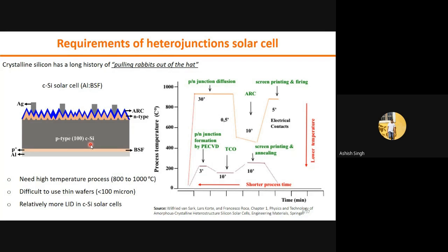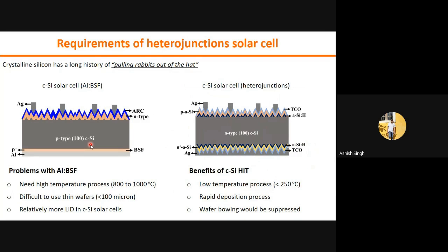So, due to this, people started thinking about using the crystalline silicon wafer and making some efficient device with heterojunction solar cell. This is the architecture of the heterojunction solar cell. In that, people use an N-type wafer to avoid light degradation, and recombination velocity also plays a key role in this. And after that, they need to deposit amorphous silicon as a hole transport layer, and N-type amorphous silicon as